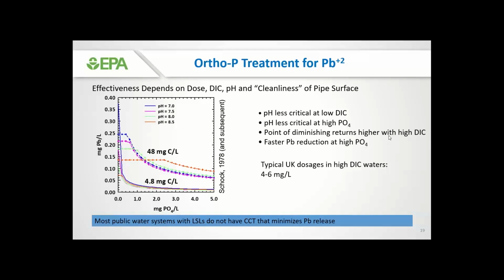So in the United Kingdom, for instance, where orthophosphate is the primary strategy for lead corrosion control, and where waters do have high DIC, high alkalinity, it's not surprising that they do rely on high orthophosphate doses ranging from 4 to 6 to be able to control lead release. In the United States, we do have systems with high DIC, such as in the Midwest, but we also have systems with low DIC as well, such as in New England, for example.